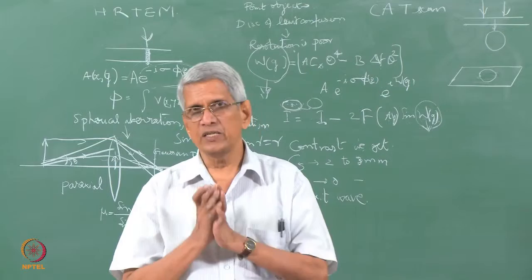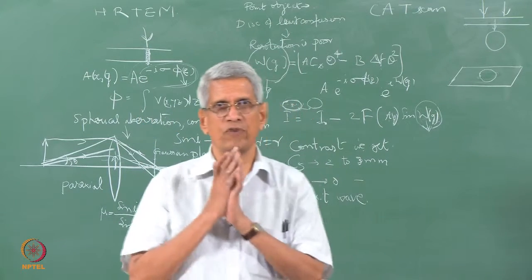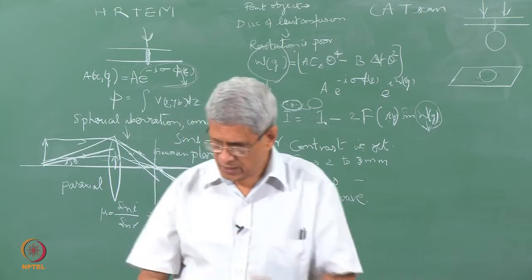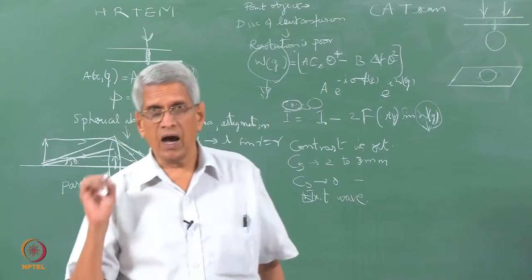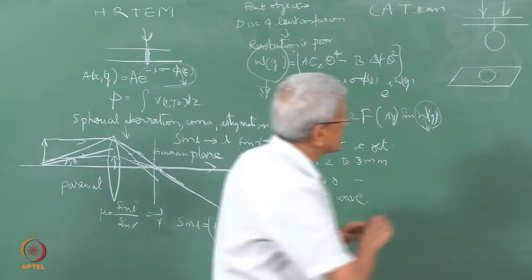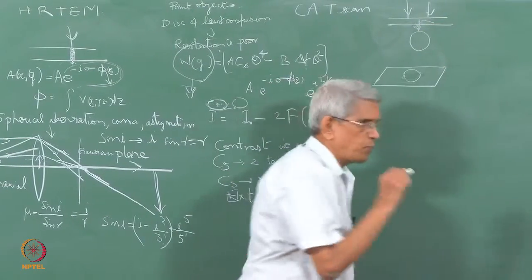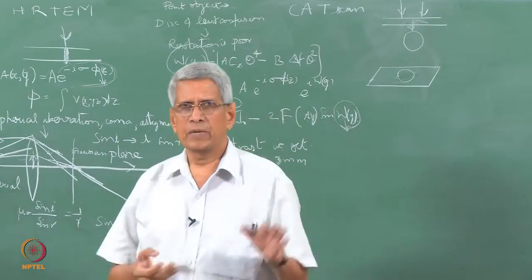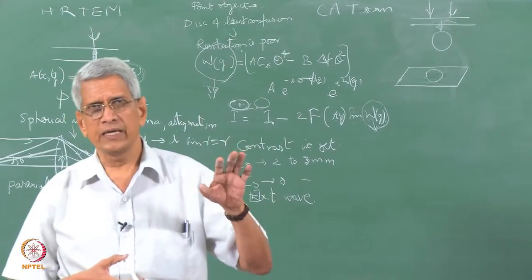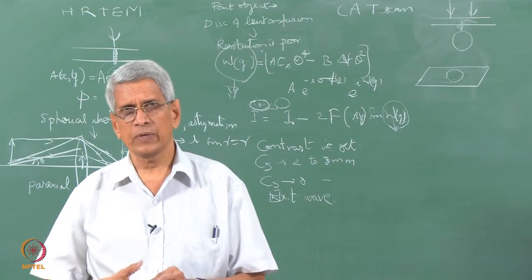In such cases, the true morphology, which is very important for many applications and understanding, can be obtained if we tilt the sample about two perpendicular axes by some small degree, normally about 1 or 2 degrees, and take the image each time.